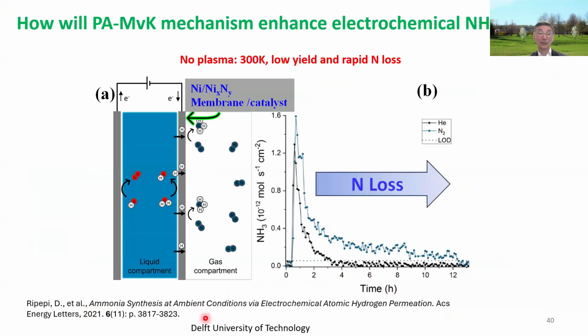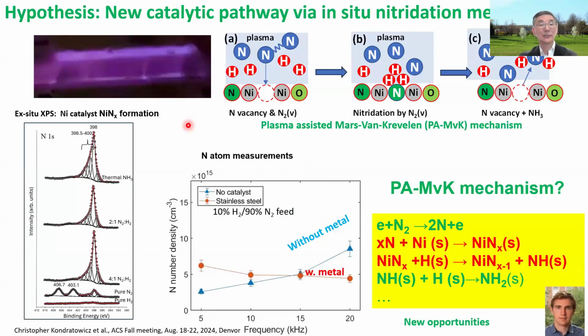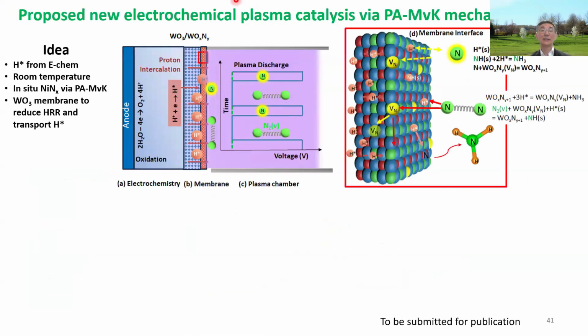There's a paper published in 2021 from Delft University. They used water electrolysis to generate hydrogen, and used a nickel nitride to produce ammonia. Initially with the nickel nitride, the ammonia yield is high and then eventually decreases. If we understand this mechanism very well, can we have a better conversion ratio? So this is the proposal I wrote to NSF: we use electrochemistry to split water to produce hydrogen. We don't want hydrogen gas; we want to suppress it to become hydrogen atoms, which are very reactive. On this side, we have plasma that generates vibrational nitrogen that can form a surface nitride, enabling the PA-MvK mechanism.